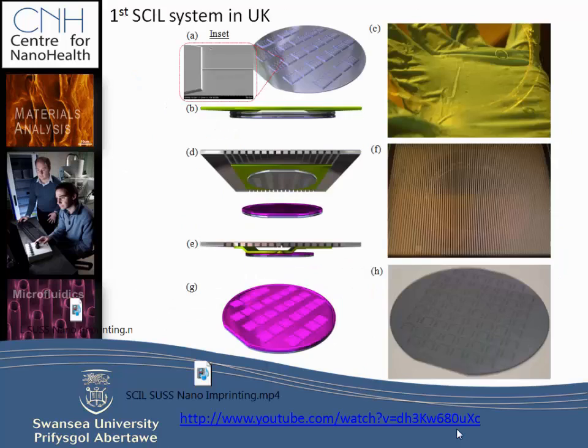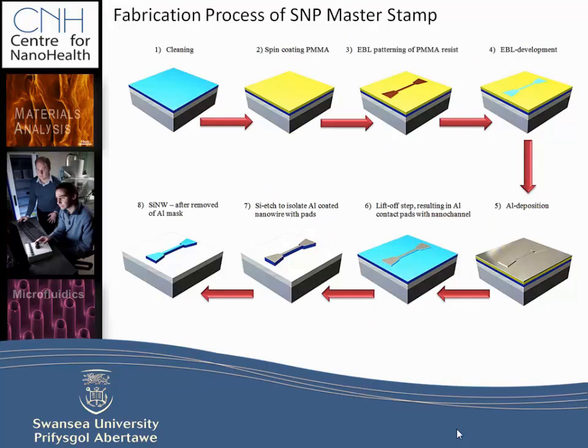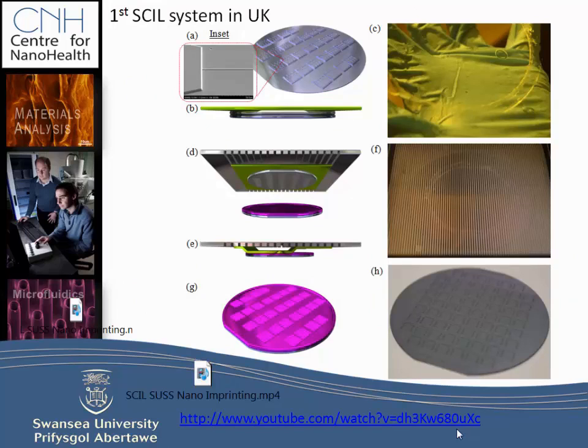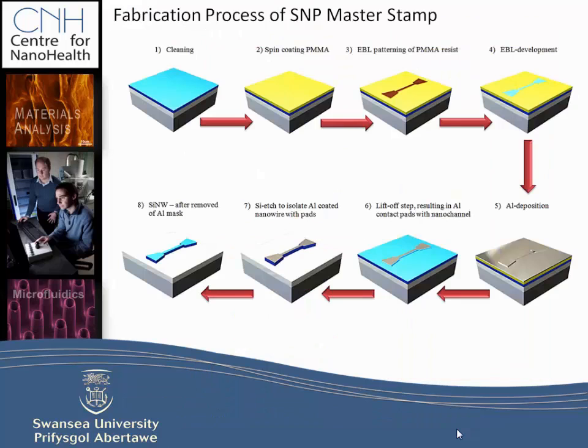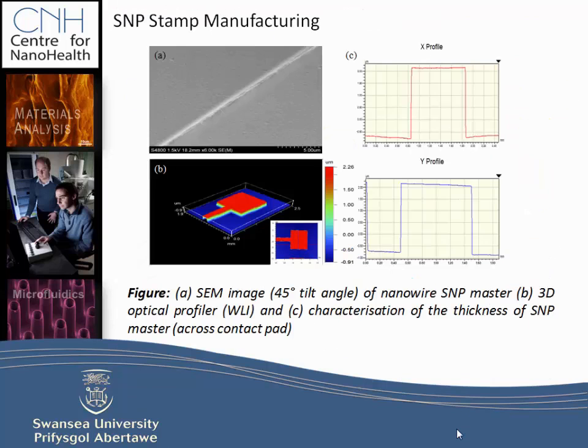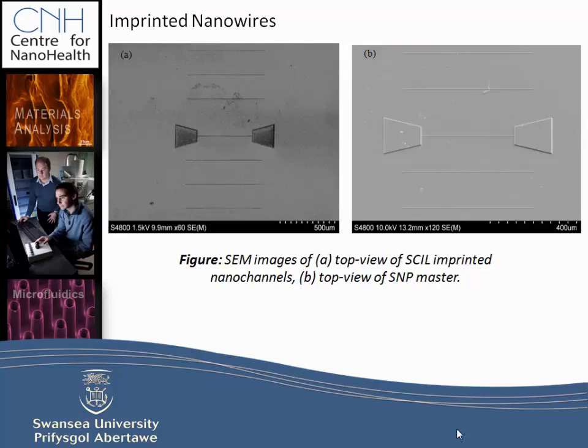So this is an overview of the nano imprint process. We create a master stamp in silicon. So this has your silicon nanowire structures. We then replicate that in what they call a soft stamp, which is using PDMS. We load the PDMS replicated stamp in the stamp holder, and then we imprint it into a polymer resist. And this imprint process, you can see, is done sequentially, so it goes down a little bit at a time, and also the retraction is done sequentially. And again, that avoids voiding or trapping of bubbles in your resist layer. And then you end up with your patterned nanowires on your silicon or SOI, silicon-on-insulator wafer.